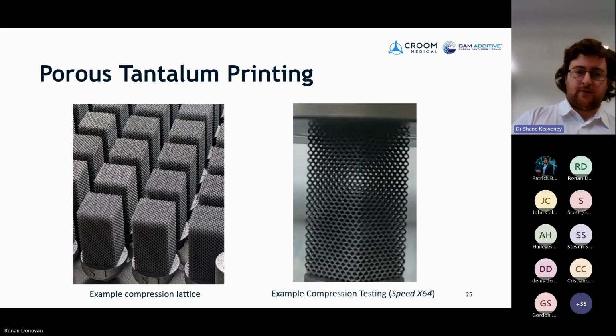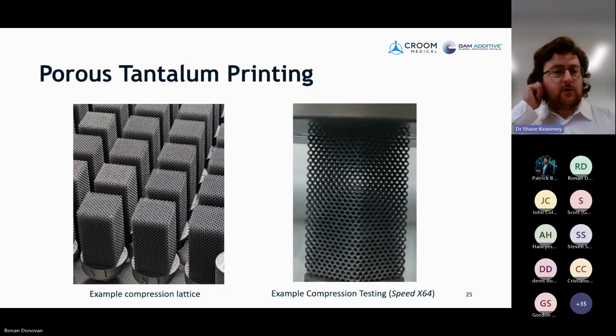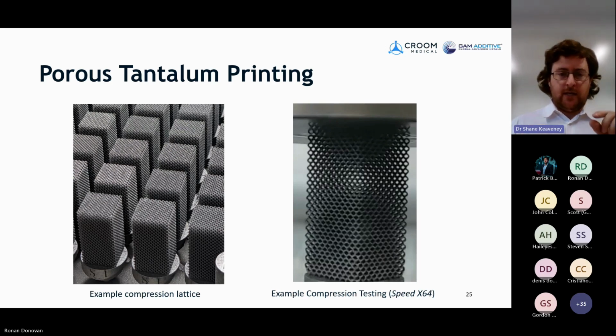The other piece then, I'll just see if this video will play. In terms of the compression tests, we've been able to demonstrate this is sped up by 64 times. But I think what this video demonstrates, so we have a compression test here being performed on one of our printed compression samples. And what we can see here is that there's a very, very nice failure mechanism, if we'd even call it a failure, more compression mechanism of the lattice structure. So the beams don't particularly fail. In fact, on inspection, we find minimal amount of beams that have actually broke at the connecting nodes, but more so they've deformed nicely, uniformly, and the sample has been easily crushed down then.